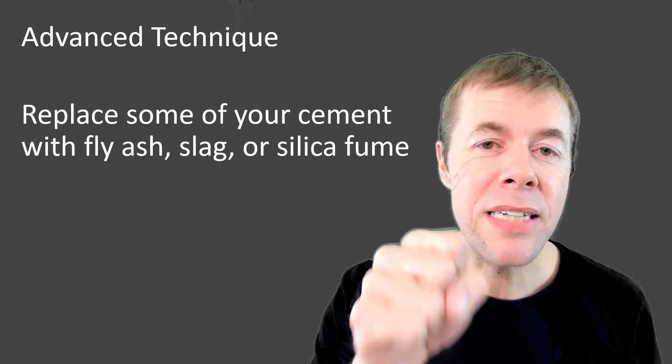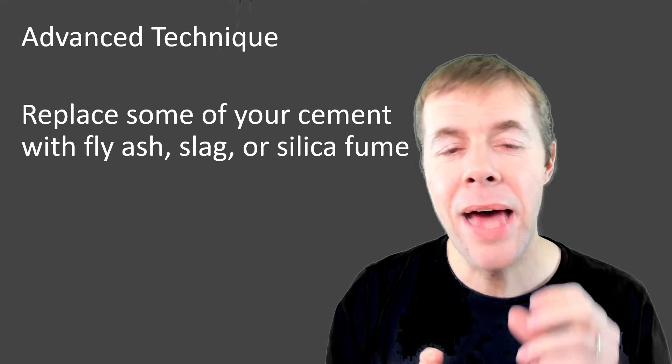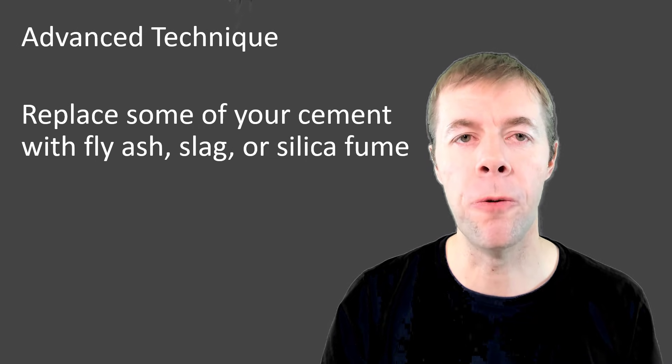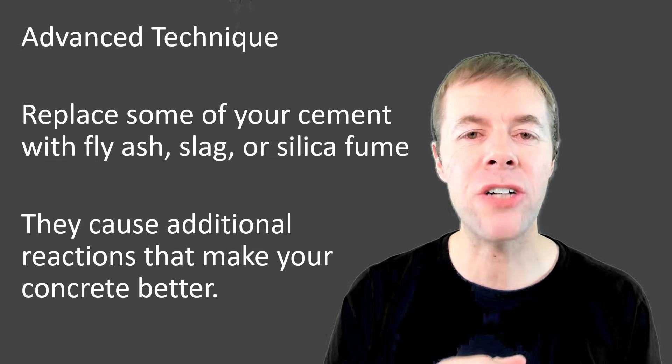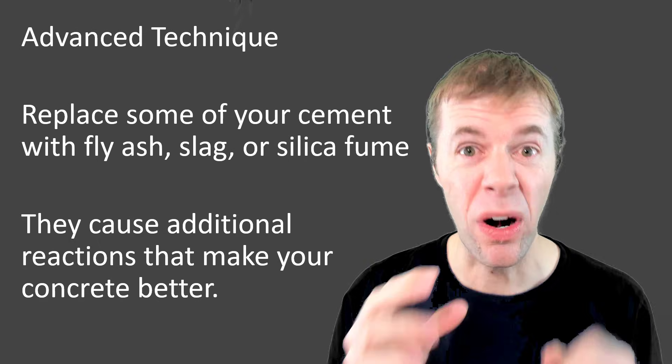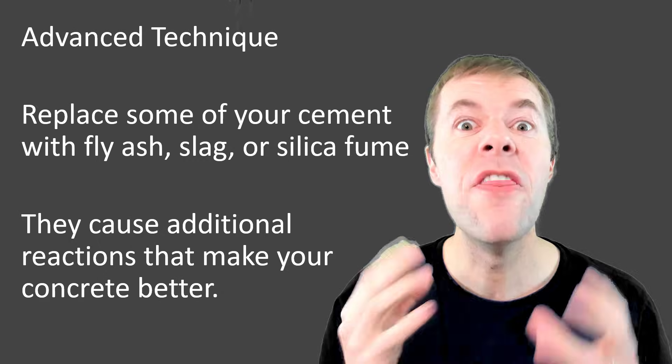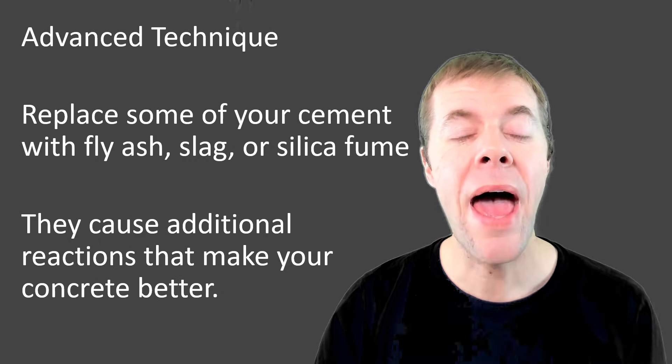So an advanced technique. Boy, this is a power-up technique. You can actually take out some of your cement and instead use fly ash, slag, or silica fume. They're going to cause additional reactions and they're going to make your concrete even better. They can double your service life by a factor of two. This is a big time change and is powerful.